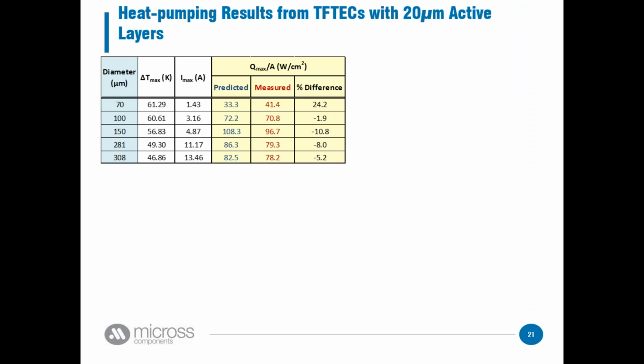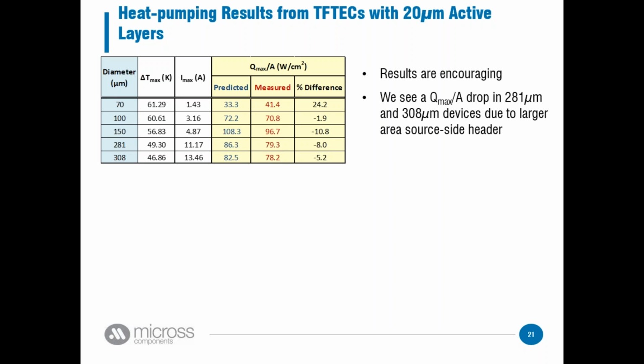We started with our 20 micron material. At the time, that was sort of our hero material, the best stuff we could do. And we actually started measuring the heat pump. We modeled and we measured it. And as you see, we're getting things like, we talked about before, you get something along the lines of 10 for the commercial modules. And we're getting numbers like 40, 70, 90. That's pretty good. These results are pretty encouraging. We're getting something that's exciting.